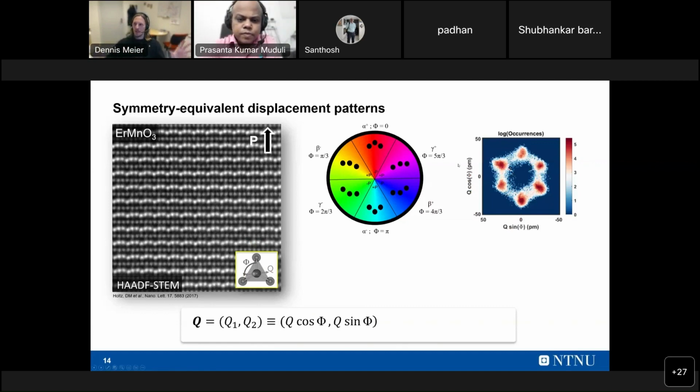What I would like to emphasize now, what I mentioned up to this point, is a purely structural effect. All this is geometry driven, and this structural order parameter is a symmetry-breaking order parameter that determines the domain state. Ferroelectricity then only shows up as a secondary effect, as a higher-order coupling term. So that's the improper ferroelectric nature of the system. You have these structural changes, they determine the energy landscape, and only due to a coupling, a small polarization shows up on top of that. That's really crucial because it means that the polarization has not much say in how the domain structure looks. It is already established, and the polarization comes up and has to live with what's already there.